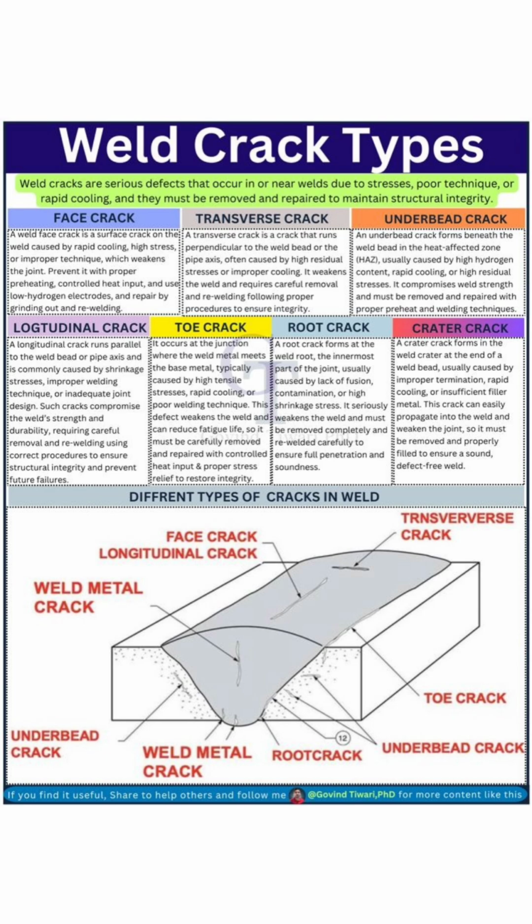Face crack. A face crack is a surface crack on the weld face, caused by rapid cooling, high stress, or poor welding technique. To prevent it, use proper preheating, low hydrogen electrodes, and controlled heat input. Fix it by grinding and re-welding.